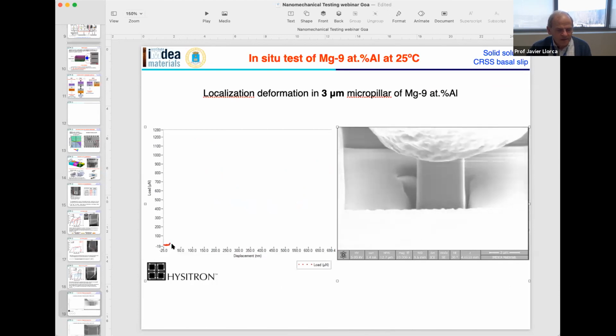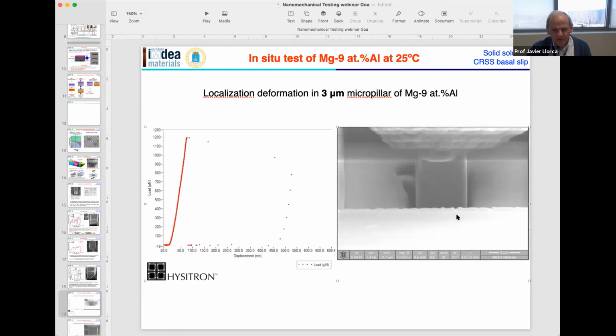Initially, you have what is a linear behavior. This is a purely elastic deformation. There is no plastic deformation because you are not able to activate dislocation sources. And as you will see, all of a sudden, there is the formation of a slip band. And this is when you have these tremors. So you can see here very, very well how the localization of the deformation happens. That's what happens when the micropillar is 3 by 3 microns.